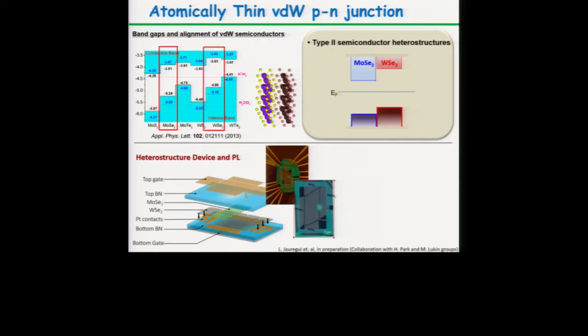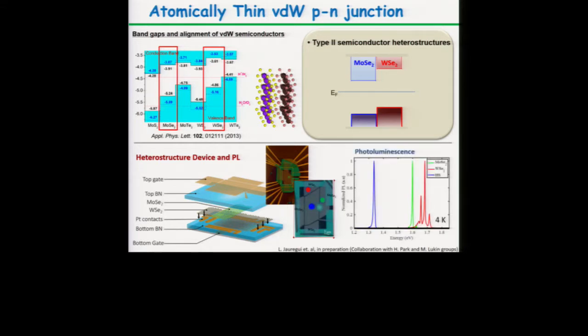This is a device example. Let me explain it maybe better in the next slide, but we have different gates. So there is a heterostructure gate. This rectangle on the bottom is actually a bottom gate for the heterostructure. We have a top gate on the heterostructure. And we also have contact gates to make the contact more transparent, to make it ohmic. And we can apply current in each of the layers, either on tungsten diselenide, which is the p-type semiconductor, or in MoSe2, which is the n-type semiconductor. If we do photoluminescence, we can do photoluminescence on tungsten diselenide or MoSe2. We see each of these individual excitons for each of the layers.